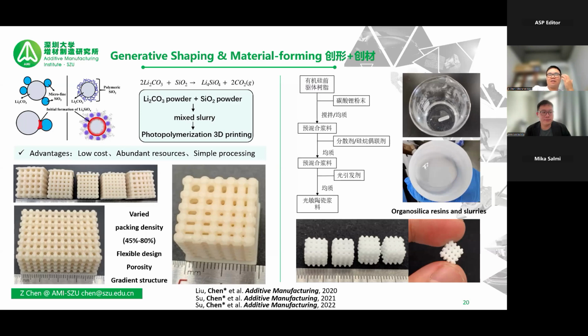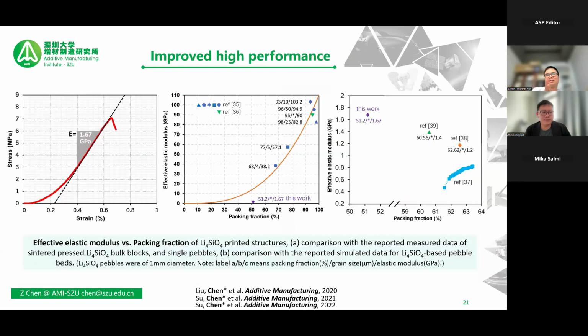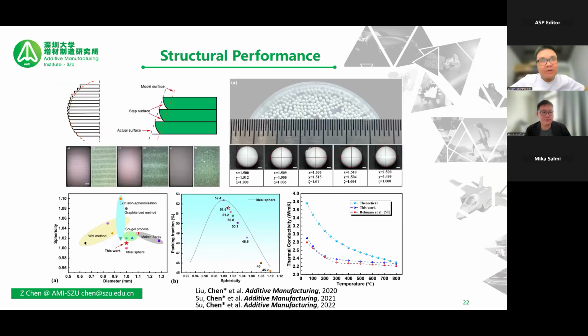And we try this material and it works very nicely. And now we're trying to expand the applicability to other materials as well. And these are some of the results we're showing here. They have very good mechanical properties as well. And also during the whole process, you can see that we have some sort of improvement because you know that 3D printing can generate a staircase effect. There's no way that we can eliminate it without some chemistry principle behind it. If you only try minimizing the layer thickness, there's always a staircase effect. But using this strategy, we can reduce the staircase effect, enhancing the surface quality.